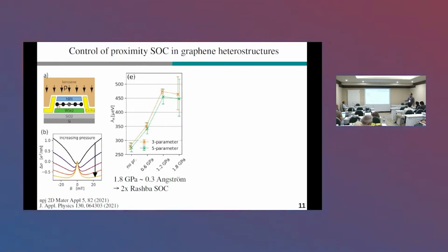And if you then do magneto-transport measurements of such a system under external pressure, you will find a crossover from the weak localization into the weak anti-localization regime. If you then fit these curves, you will find that the Rashba spin-orbit coupling can be increased by roughly a factor of 2 with an external pressure of about 1.8 gigapascal, which corresponds to a reduction of the interlayer distance by 0.3 angstrom, which is around 10% of the interlayer distance.